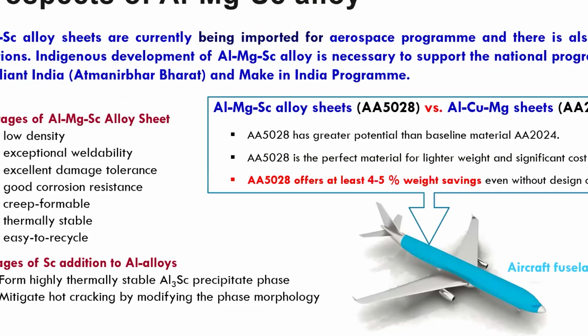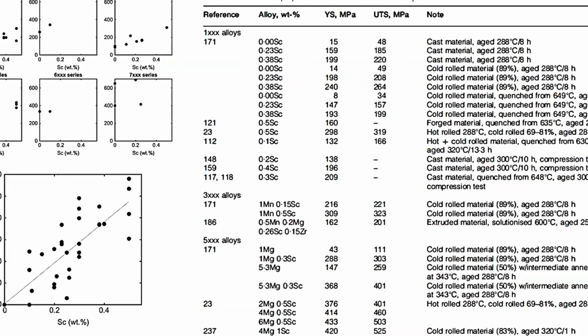So let me take one example, that is scandium. When scandium is added to aluminum, for example, as I hope you remember, these structures are made of 2000 series alloys, an aluminum copper alloy with heavy weight. And if you are able to replace this copper alloy with aluminum magnesium scandium alloy, 5000 series, you directly have a weight saving of 4 to 5%. And more than that, this particular alloy has exceptional weldability, excellent damage tolerance, and better corrosion resistance than that of the 2000 series. So these types of alloys are also being used, and strength is also high.